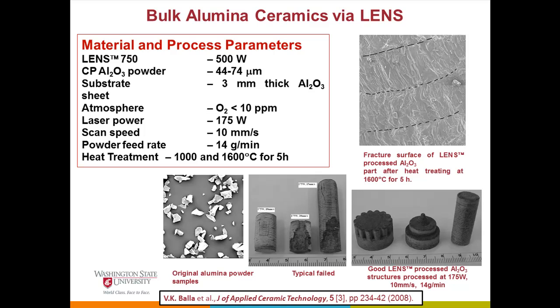The second thing is we're using an oxygen partial pressure level of 10 ppm or less while building aluminum oxide. What we found in our aluminum oxide parts is that because of the low oxygen level, they look black, meaning they are actually low in oxygen - so it's not Al2O3, but Al2O3 minus delta, meaning they are oxygen deficient. That's the reason we tried heat treating them at 1000 and 1600 degrees Celsius, to understand if any property changes could happen.